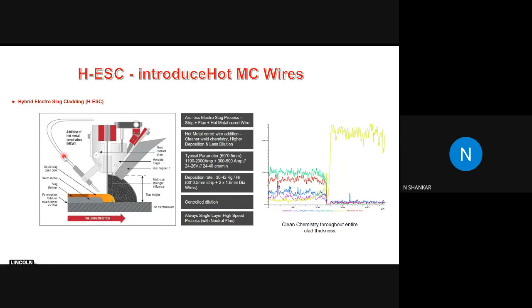Also, this metal core wire will give you an additional benefit of adding any additional material composition you want to provide higher corrosion resistance, higher strength, whatever is required. So this can be done by adding a metal core wire to the strip cladding process. So that is what is called hybrid strip cladding applications. When I make it hybrid by introducing a metal core wire, A, I increase the deposition rate, B, I can make higher, thicker cladding or walls, and C, I can have higher mechanical strength by adding additive materials into the metal core wire. Metal core wire composition can be designed as per my requirement, and it has all the other benefits of electroslag strip cladding applications. So that is hybrid electroslag strip cladding application for you.